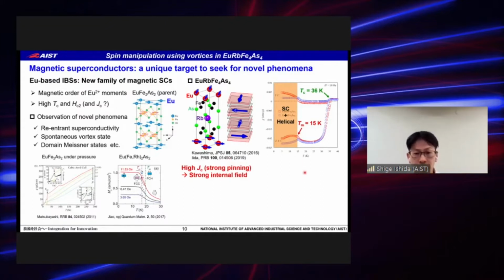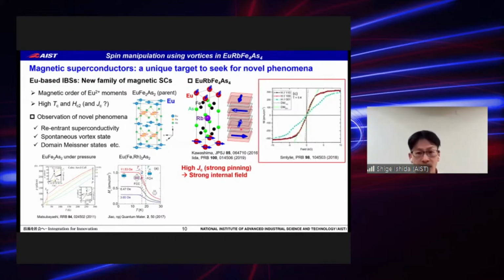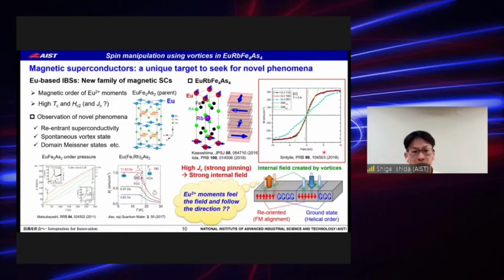Note that magnetization field measurements suggest that the europium moments are easily reoriented by magnetic field. You can see the saturation moment indicating the ferromagnetic alignment of europium moment in magnetic field. We then came up with an idea that if vortex pinning is strong and creates a strong internal field, the europium moment would feel the internal field and follow the direction of the pinned vortices, as illustrated here.